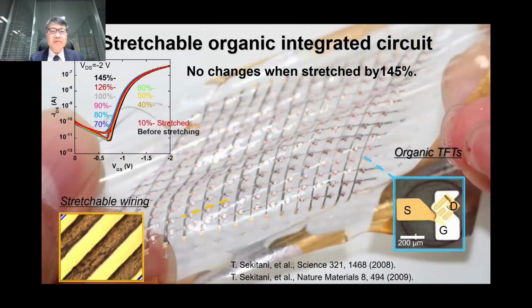And immediately after manufacturing the simply flexible electronic skin, we instantly recognized how important it is to achieve mechanical stretchability. Indeed, without stretchability, we cannot apply the e-skin onto a movable part like a joint of an arm, or it is impossible to put the e-skin onto a three-dimensionally curved surface like a robot body. So to achieve the stretchability, our approach is very straightforward. First, we put a two-dimensional array of rigid islands that are embedded into the rubber substrate, and then print the organic thin film transistors on the rigid islands. And finally, electrodes could be connected by utilizing elastic conductors.